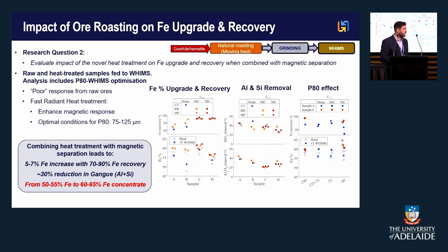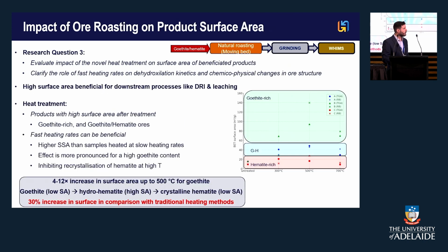So it was really a good achievement there. And also, when it's coupled with magnetic separation or with leaching, I have a slide on that, we are also able to really remove a lot of alumina, silica, and phosphorus. So we were able to prove that on average we can move from an uneconomic iron ore to an economic one, and potentially also start fitting in the high grade region for DRI.